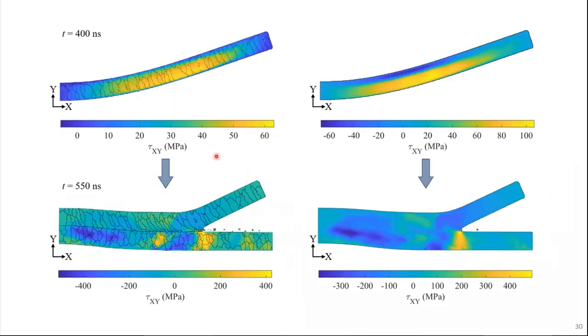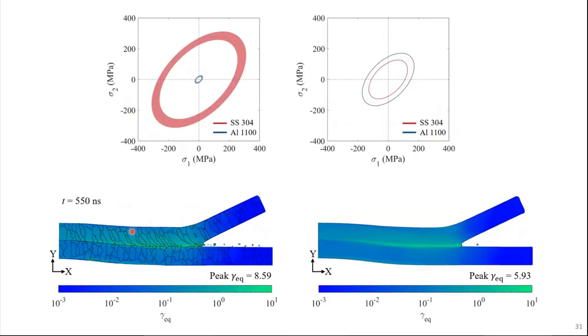To give you an idea of what happens with the shear stresses, with microstructure and without microstructure, firstly, you notice there's a difference in the color bars. Secondly, you'll notice there's a difference in the actual pattern that we're getting. So again, that shows us how incorporating a microstructure makes a difference in the prediction. Again, to give you an idea of how it affects the equivalent plastic strain, what we've done first is plot the von Mises yield criterion, or max distortion energy yield criterion.